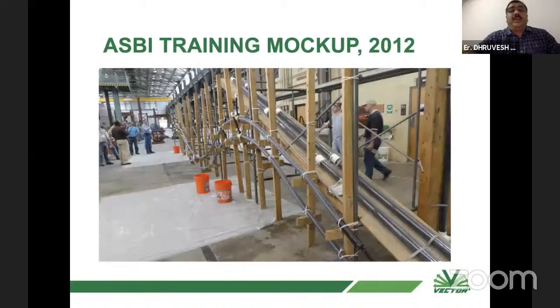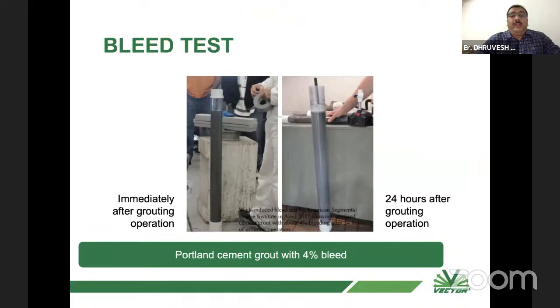So the American Society has done a mock-up also to know how the grout behaves. A real-time mock-up was done, and they developed a bleed test. Immediately after grouting, they made a glass tube, a meter in length, and poured the grout. They found that at just 4 hours there was no bleeding, but at 24 hours you can see the bleeding at the top. So you can simply have your grout tested at your site. You can have a tube like this, maybe of 3-inch diameter, place a tendon in it and the end cap, and when you wait for 24 hours, you will find this bleed, and this is what is detrimental. This is very, very normal in the case of a cement water grout.